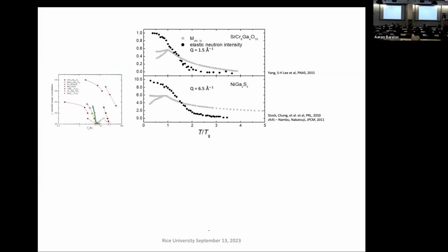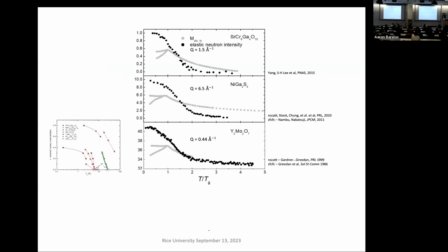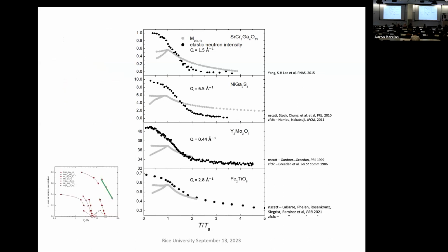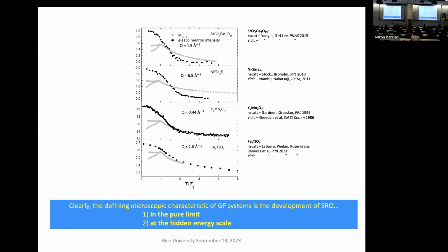There it is on our phase diagram. Here's nickel gallium sulfide. Here's yttrium molybdenum oxide. So kagome spin 3/2, triangular spin 1, pyrochlore spin 1/2. Yeah, I think spin 1/2. And this is spin 5/2, but it's a structure called the pseudo-brookite structure. The triangles aren't easy to see, but it's nevertheless extremely frustrating, and this shows the same behavior. So these are all the data I could find. Okay? So clearly the defining microscopic characteristic of geometrically frustrated systems is the development of short-range order in the pure limit and at the hidden energy scale.